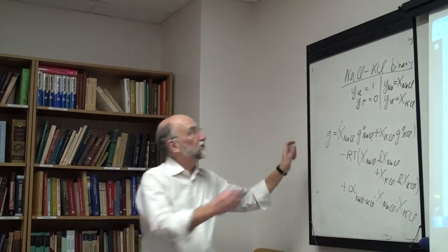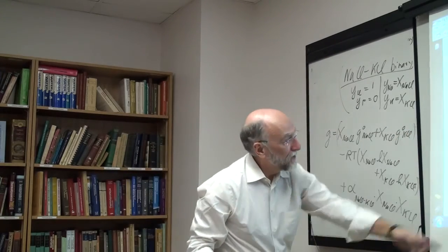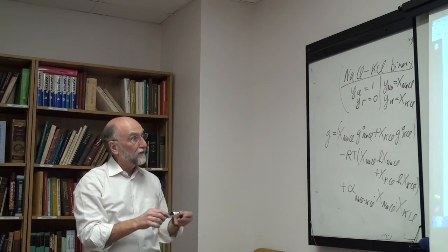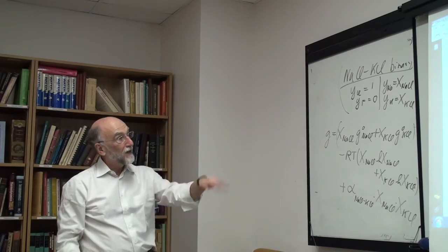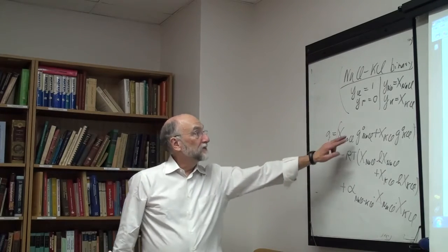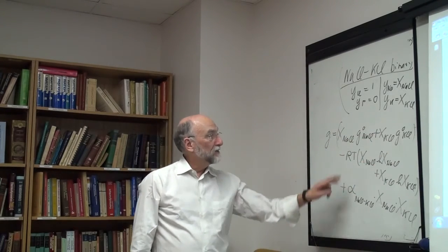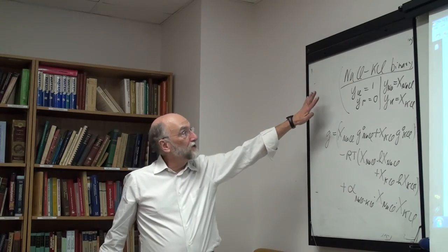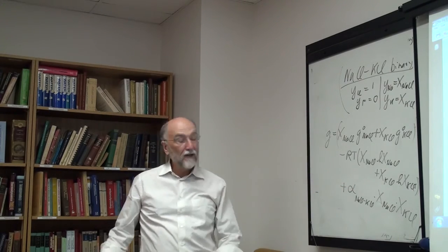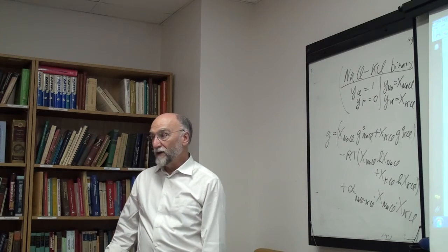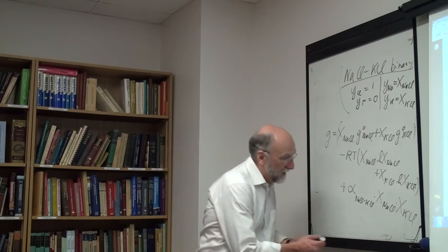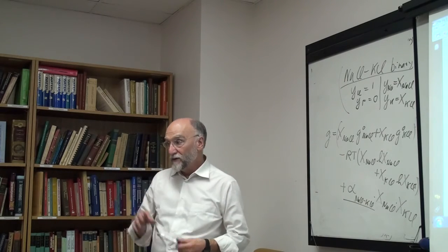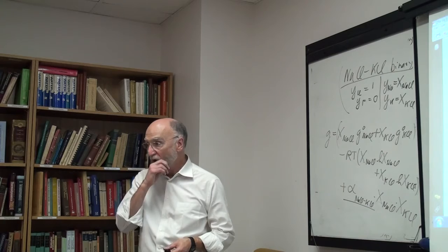Making these substitutions into this equation, you get a binary mixture of A and B. Sodium chloride is A, potassium chloride is B: X_A G naught A plus X_B G naught B plus RT X_A ln X_A and so on. So you've forgotten the chlorine sublattice, and this is just mixing sodium and potassium on the cation sublattice. The interpretation of this alpha term is the second nearest neighbor interaction energy.